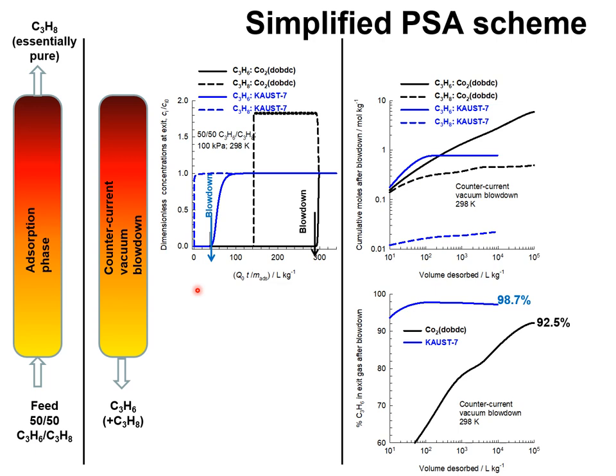The message that emerges is that to achieve high purity, the uptake of propane in the adsorption cycle should be close to zero. We need total exclusion of the saturated component; otherwise, the purity requirements are difficult — nay impossible — to achieve.